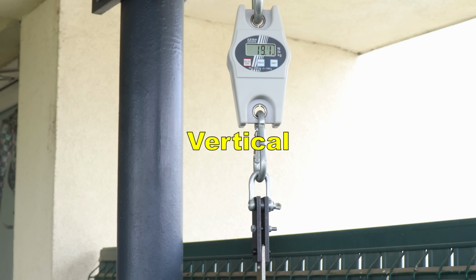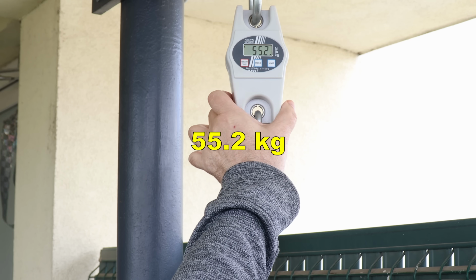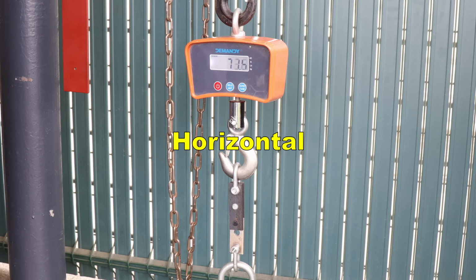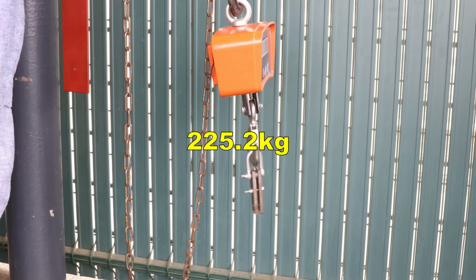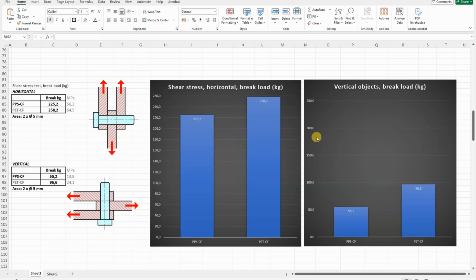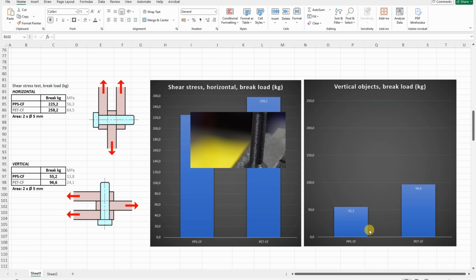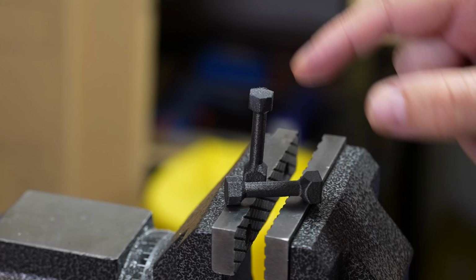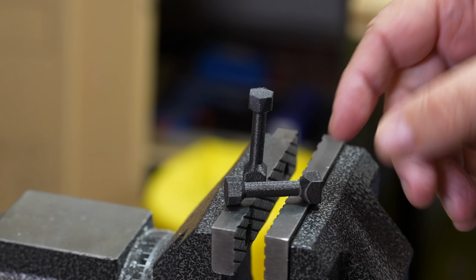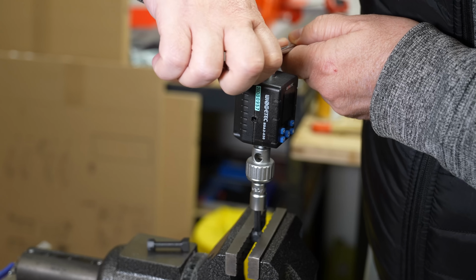Is this okay? Shear test, and first with the vertically printed test object. And it's affected by that weaker layer adhesion. And now horizontally printed, and I'm expecting higher loads, that's why I changed the scale here. PET-CF is stronger in both cases, but this value for the vertical object can be improved if we use those optimal settings for the better layer adhesion I explained earlier. The twist test with horizontally and vertically printed test objects with the same dimensions. This is horizontally printed.